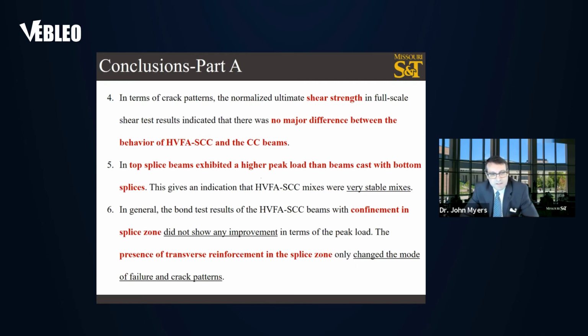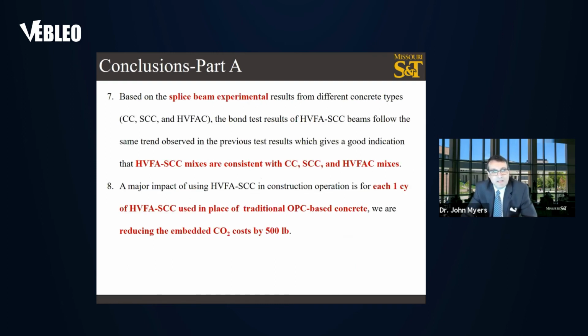Confinement in the splice zones did not show any significant improvement, and the presence of transverse reinforcement in the splice zone changed the mode of failure and the crack patterns only. Splice beams experimental results showed that the high volume SCC mixes are consistent with conventional concrete, self-consolidating concrete, and high volume fly ash concrete.